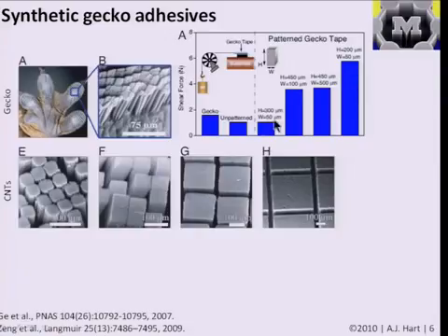And for example, if you make an unpatterned surface, basically where you just have a full area film of nanotubes, you might locally get strong adhesion, but because you can't deform the individual pillars to adapt to roughness in the surface, you don't get nearly as much adhesion as you do if you pattern the surfaces. And they have different results for different heights and widths of the pillars.